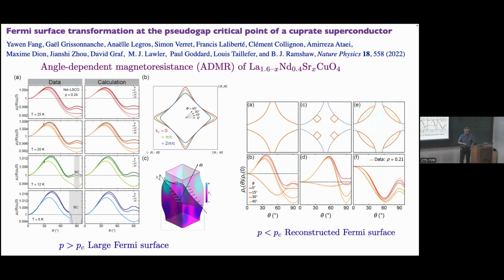In this particular paper, the calculation they're doing is based on having long-range antiferromagnetic order. Only trouble is there's no long-range antiferromagnetic order here at all. So it's a model that seems to work, but you don't quite understand why. All right, so that's the angle-dependent magnetoresistance.